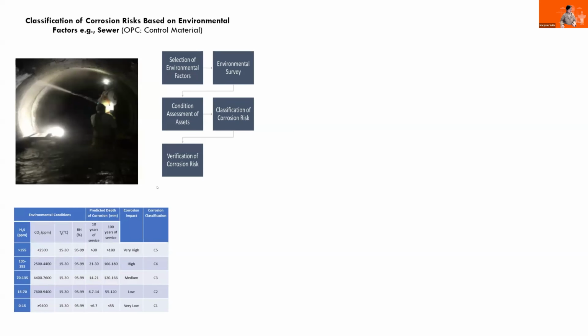And to validate that, what we've done is we then installed a series of alternative cementitious material in this environment. And then we also measured the relative corrosion. And this is an example of one material that we have installed. So we could see here that we do have different levels of corrosivity or corrosion rates depending on the different aggressiveness, C1 being the lowest, the least aggressive, and C5 being the most aggressive. And essentially that validates that the classification that we've developed for OPC also works for other types of cementitious material.